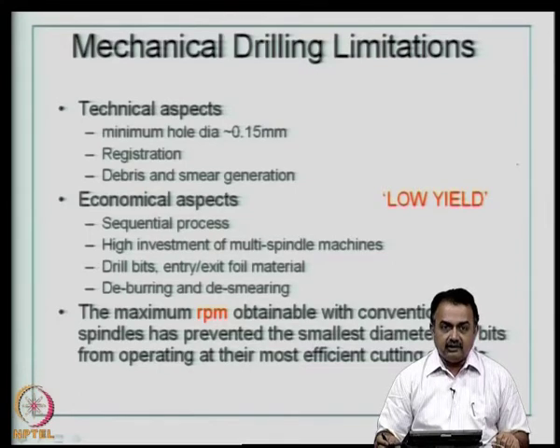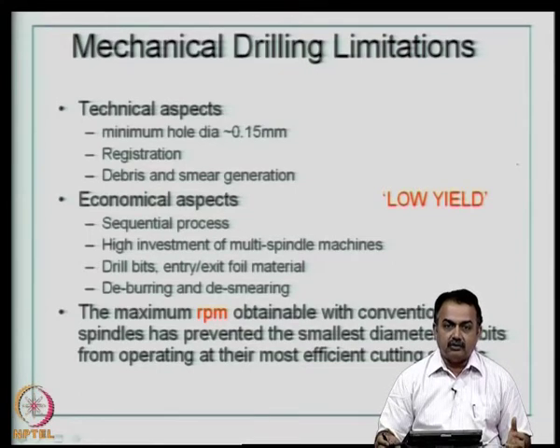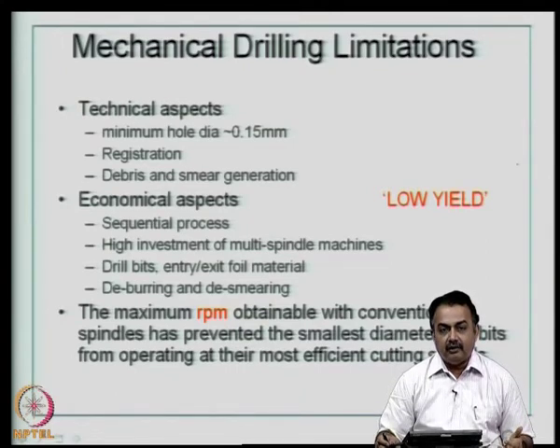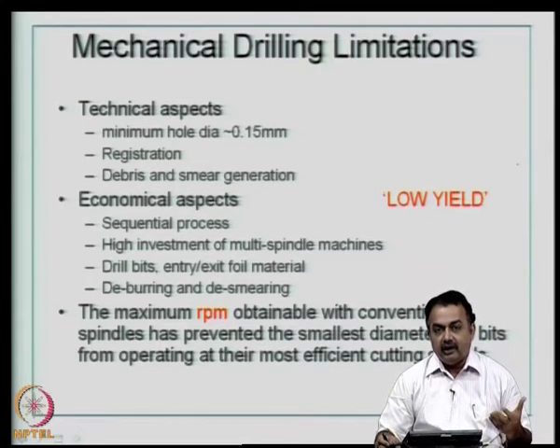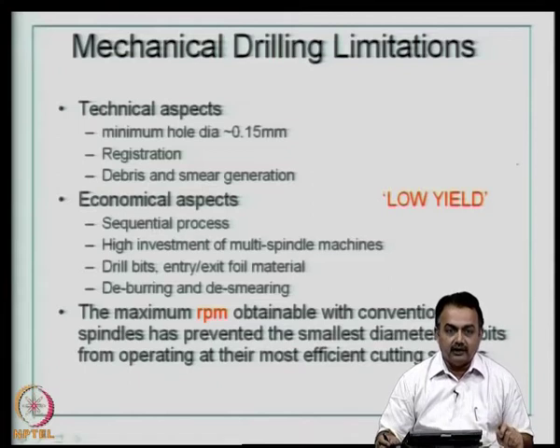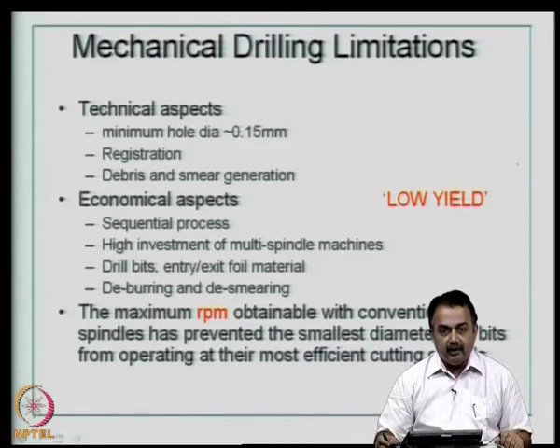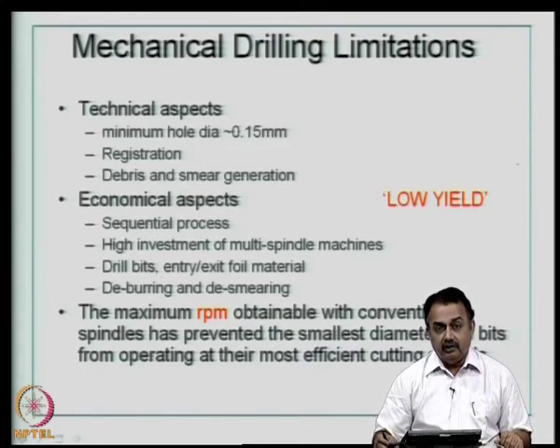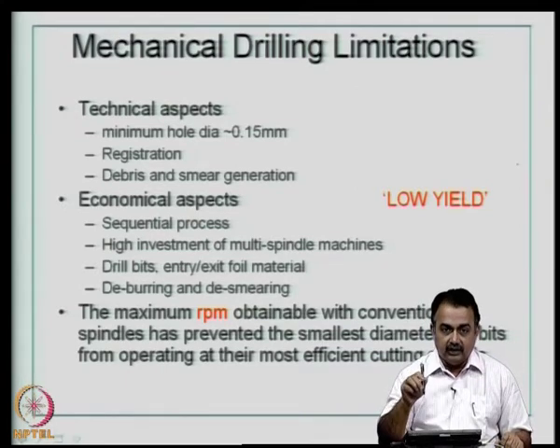The basic reason is that mechanical drilling has its own limitations, because the minimum hole dia you can create is 0.15, registration is a problem, and debris and smear generation during drilling can block the holes. You need proper hole wall preparation before electroless plating. The economical aspects, it has got low yield because you are going to depend on sequential drilling process and it can take time.